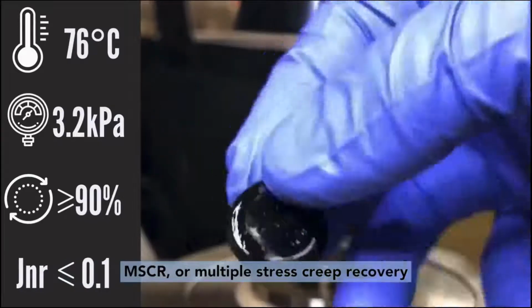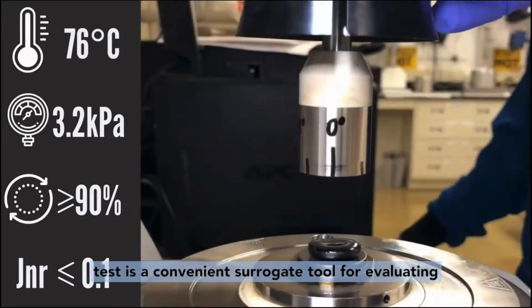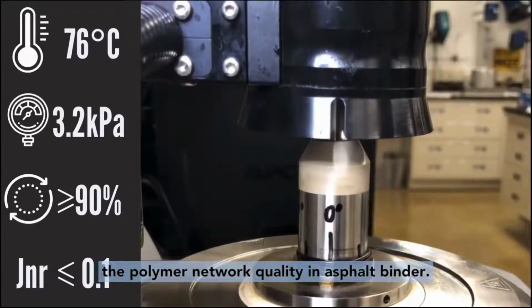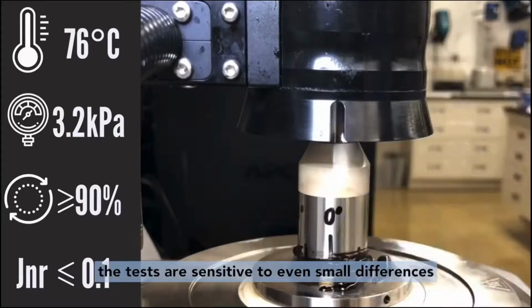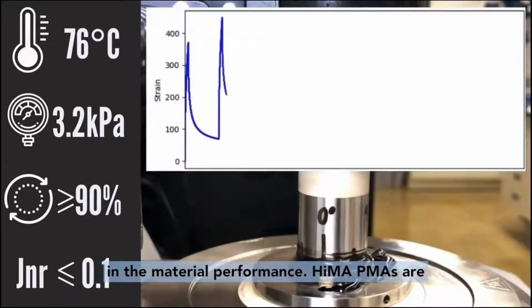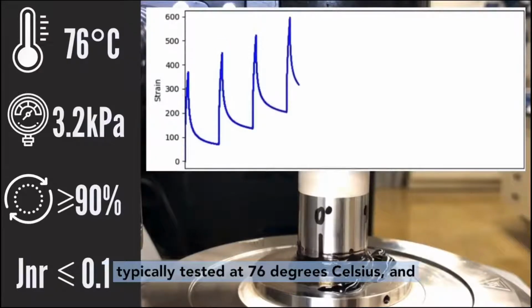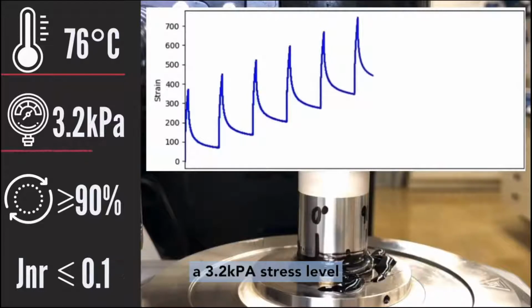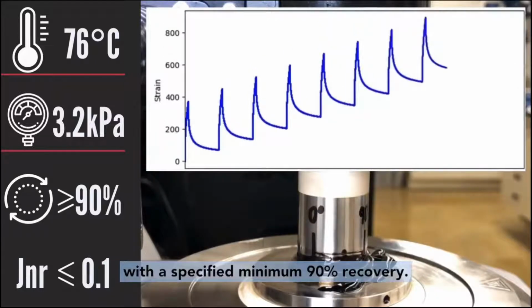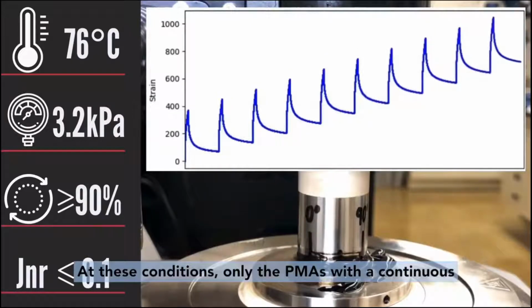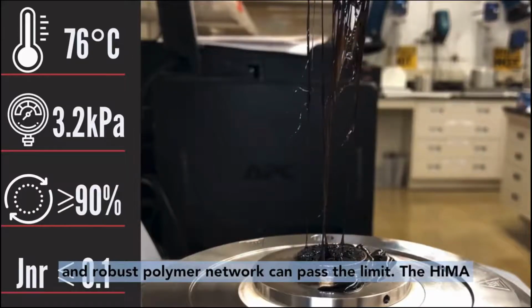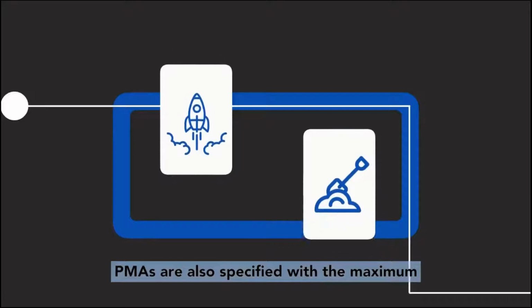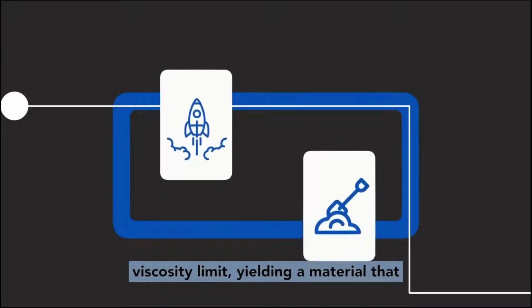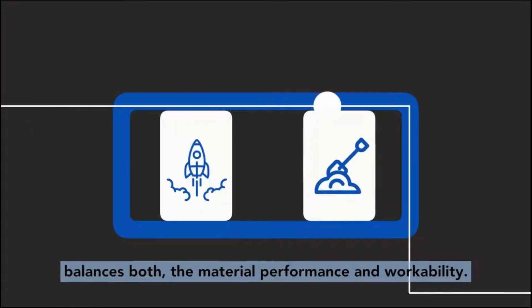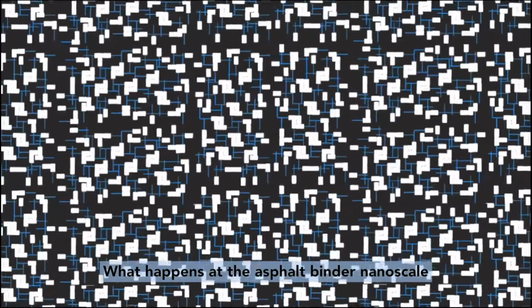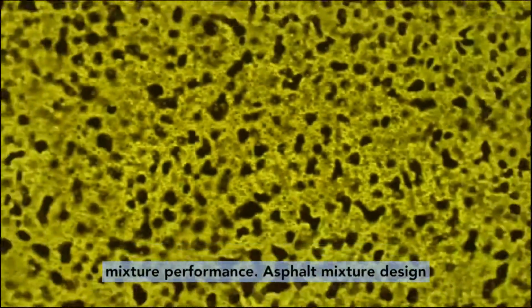MSCR, or Multiple Stress Creep Recovery Test, is a convenient surrogate tool for evaluating the polymer network quality in asphalt binder. Dynamic shear rheometers used to perform the test are sensitive to even small differences in the material performance. HiMA PMAs are typically tested at 76 degrees Celsius and a 3.2 kilopascal stress level, with a specified minimum 90% recovery. At these conditions, only the PMAs with a continuous and robust polymer network can pass the limit. The HiMA PMAs are also specified with a maximum viscosity limit, yielding a material that balances both the material performance and workability. What happens at the asphalt binder nanoscale has a set of very profound effects on the asphalt mixture performance.